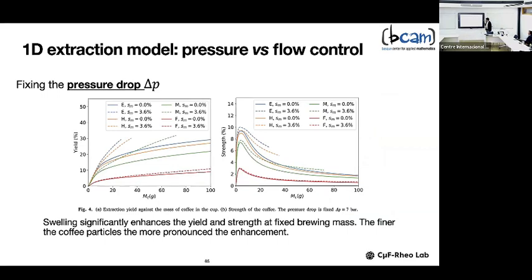Okay, here we go to the last message that we would like to transmit: if you do an extraction at constant pressure drop, as we saw earlier, there are some variations. Swelling has an effect, as you can see, especially on the strength. There is a variation which depends on the degree of swelling. Here we have assumed, for example, just 3%, and even with this 3% swelling, we already have a change in the curves, and also with different powders. Everything is mixed, different powders and different degrees of swelling. There's a lot of variability when you perform extraction at constant pressure.